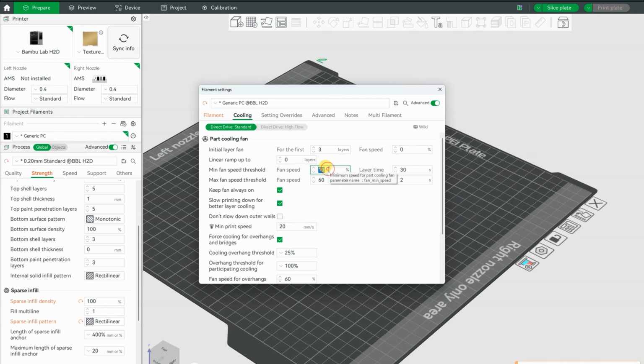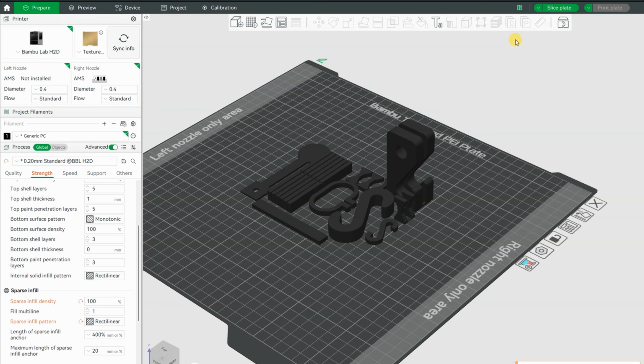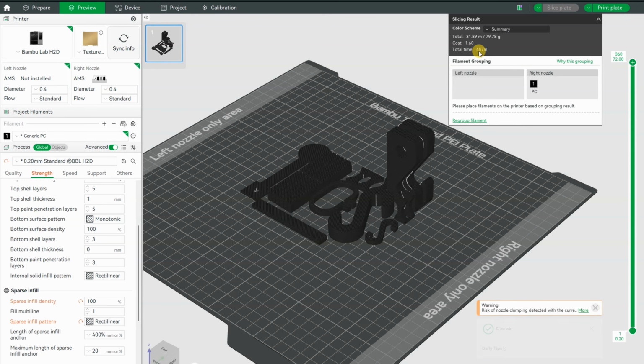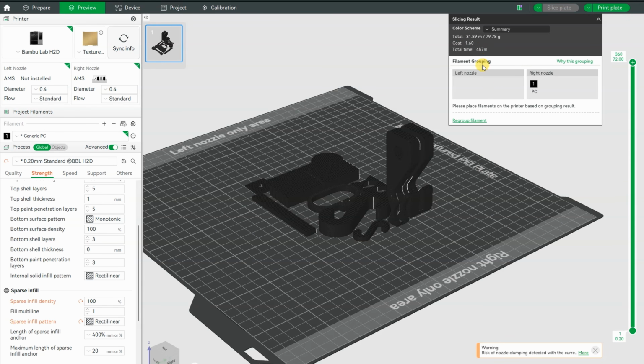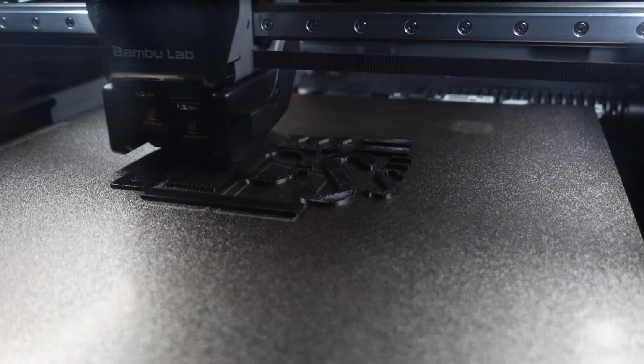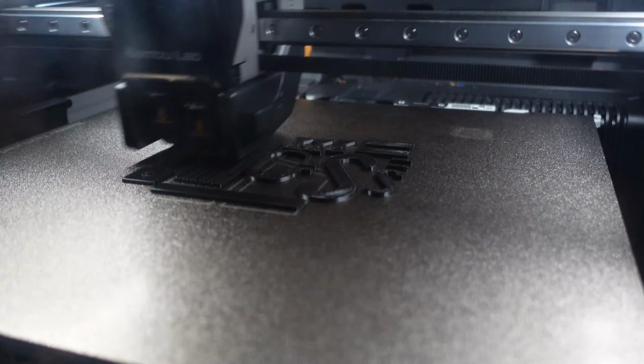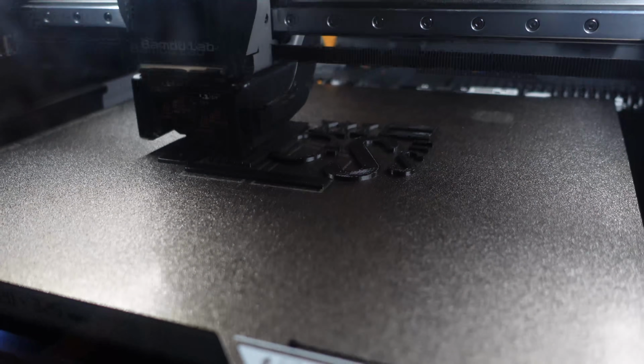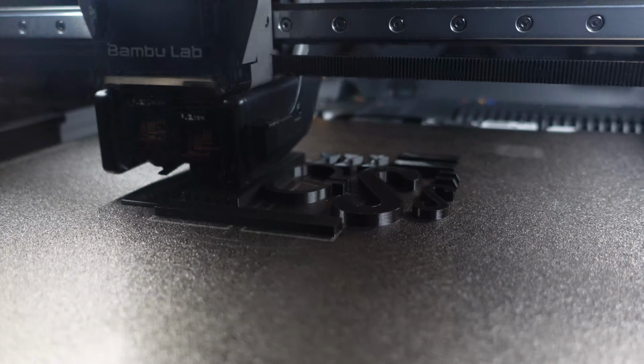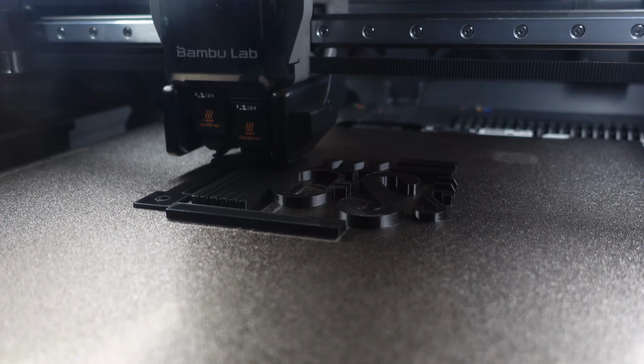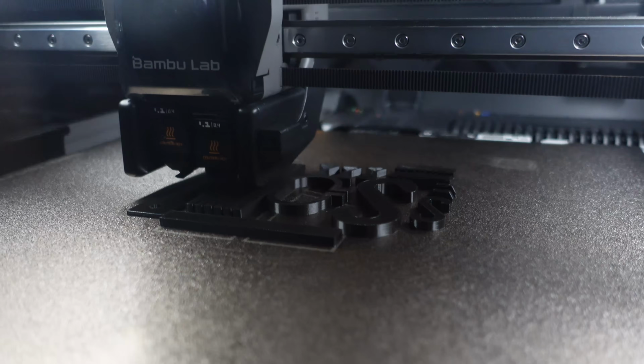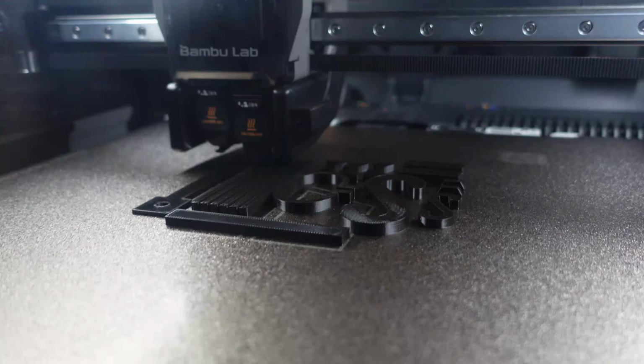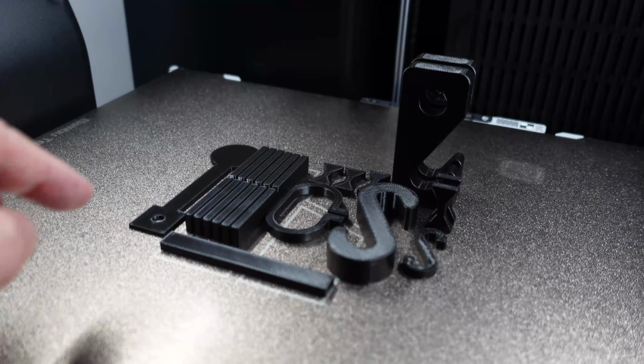And the cooling I'm reducing, it will be between 0 and 30%, based on experience from my review video. But of course this minimal layer printing time of 2 seconds is too short. It will be 5. And the printing time will be approximately 4 hours. H2D. And last time when I was printing with this filament, I used glue on a textured PEI sheet, but I'm curious if it will work without glue too. Looks like it will be fine, it passed that critical point. The warping may appear because of the shrinking of the material, but also because of weaker bed adhesion, but so far it's okay. The bed cooled down completely.